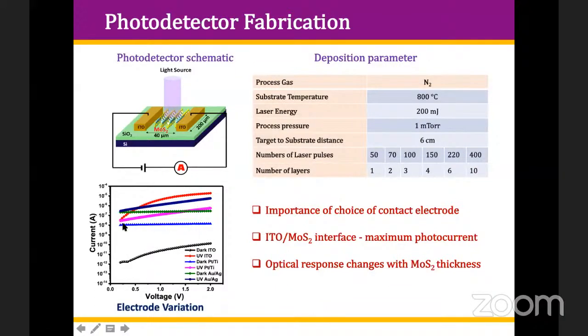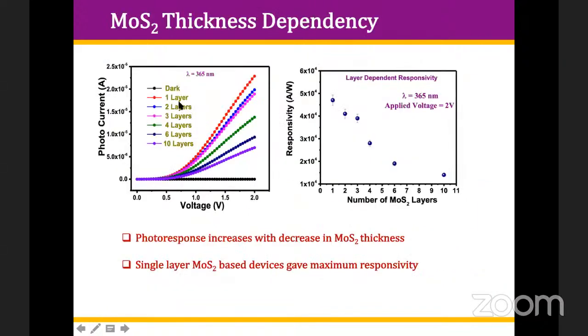As far as platinum and titanium are concerned, this is the dark current and this is the photocurrent, which is very less. Similarly, this is the dark current for gold and silver, and this is the photocurrent for gold and silver. So I will say out of these, the best photo response comes out for the ITO electrode. The ITO-MoS2 interface gives the maximum photocurrent, and the optical response of the system also depends upon the thickness. So we tried to change the thickness of the MoS2 in the same configuration from 1 layer, 2 layer, 3 layer, up to 10 layer. And you can see this is a dark current.